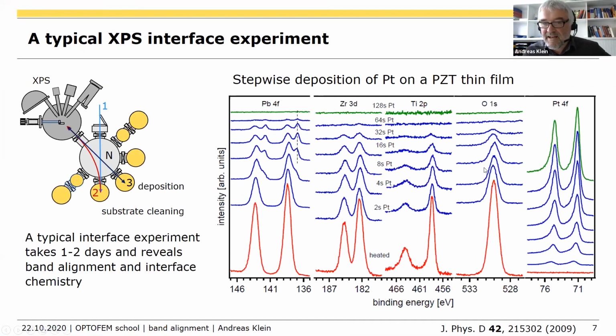Here, in this case, not. That looks pretty symmetric, but this is already a little bit asymmetric. But if you take the sample and just bring it inside the XPS system from air, there will be a peak. And that's simply adsorbed water or adsorbed hydroxides, surface species. If you really clean your surface, these shoulders, which are usually attributed to oxygen vacancies, are gone.